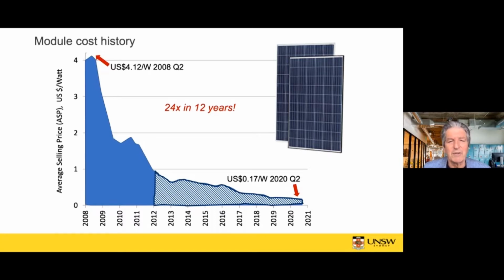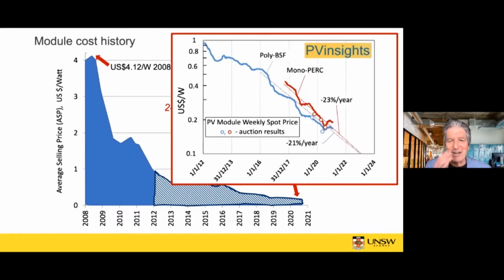But over the next 12 years, we've seen this dramatic reduction. So about this time last year, they were selling for 17 cents a watt. So that's 24 times cheaper. So a module like that of 350 watts would cost $50-something. So, a dramatic change from $1,000 to $50-odd. And that's had a big impact on the way you can use the technology. So, quite some dramatic things happening to the left of the previous graph, and then more stable conditions past 2012, the shaded region. And this just shows that shaded region, the data there, on a logarithmic plot.